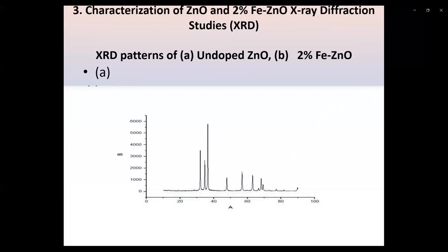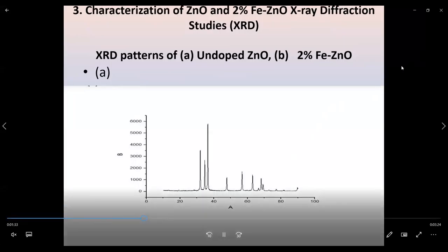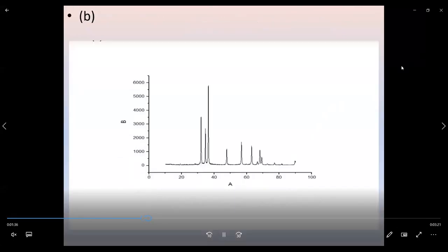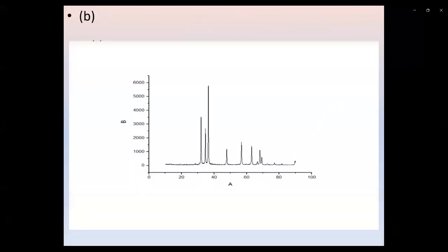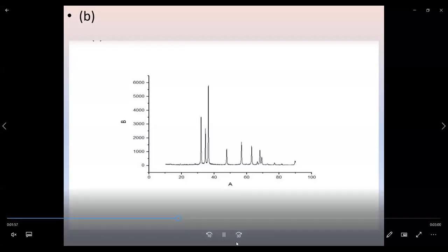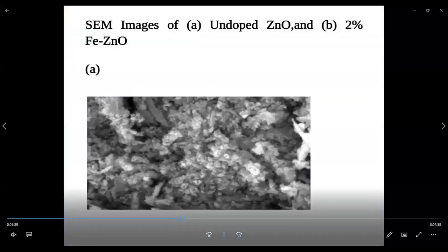The undoped zinc oxide nanoparticle shows only one highest peak at 40. So this is calculated with the help of the 2 theta formula. Based on that formula, it is prepared and it shows the hexagonal wurtzite-like structure. This is an XRD pattern of a 2% iron-doped zinc oxide. The doped and undoped have the same structure, and any difference is not observed. The same position peak is observed. It shows that the doped structure also has the hexagonal wurtzite-like structure.